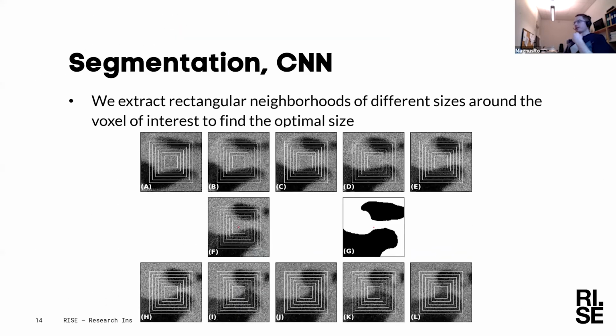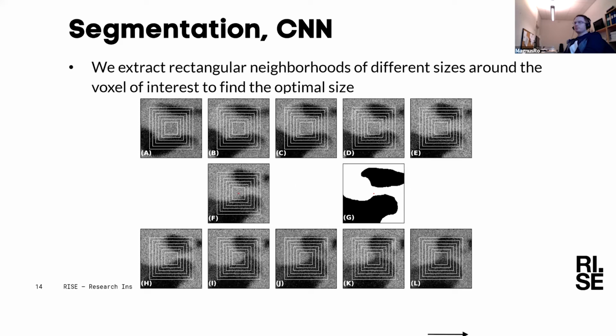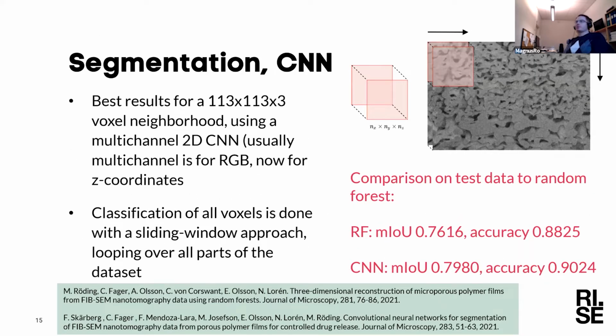We got better results from the CNN than we got from the random forest. And you see here some examples of the different sizes of these neighborhoods that we evaluated. And what we found, which is interesting, is that we used a sliding window approach where we trained the CNN to classify a single voxel. And then in a sliding window approach, we just loop through the image line by line. I understand that this might seem a little bit odd considering that it's general consensus that fully convolutional networks would be state of the art for classification tasks like this, but we actually tried that and we weren't really able to get so good results with that.